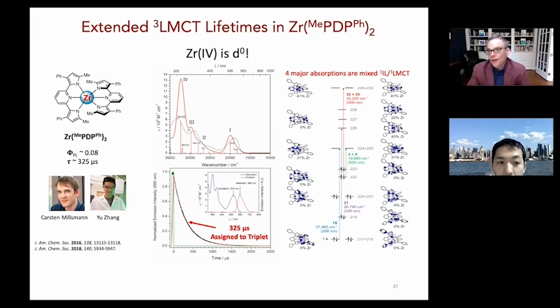It's a lowest energy triplet metal to ligand charge transfer excited state, but the singlet is only about 1400 to 1800 wave numbers above it, depending on the compound. So you can thermally activate to the singlet MLCT state at room temperature. Copper has the same processes, except that they're metal to ligand in character, and there's no ligand centered character in the copper complexes. It's all 100% MLCT.